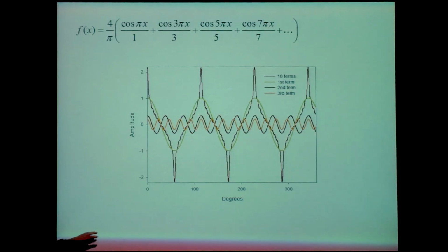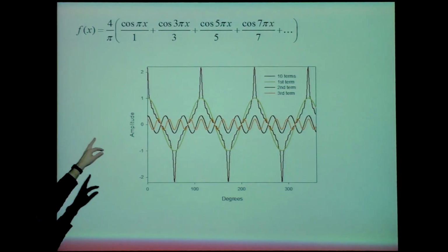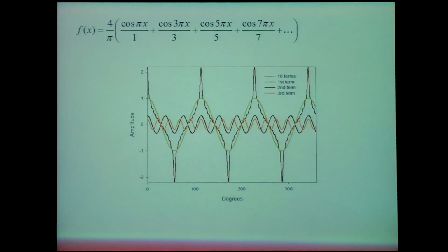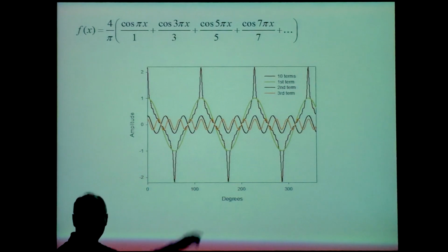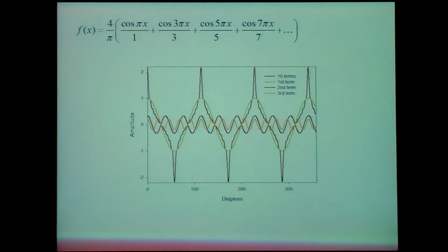Now, there's something that's important here as well. Can you see from that Fourier transform about the first term, the second term, the third term, and the fourth term? Notice how they're divided by 1, by 3, by 5, by 7. When you look at a diffraction pattern, it's fairly intense in the center. That's the low resolution term. And as the diffraction goes out, the intensity goes down. This is what we're seeing. This is why it's divided by 3, divided by 5, divided by 7, on average. That's why the information is becoming less intense as you go out, as you get higher and higher detail.